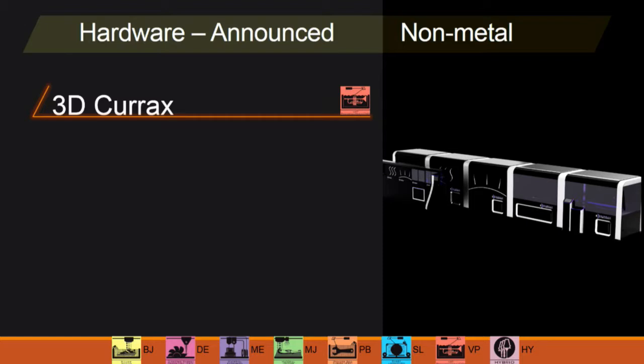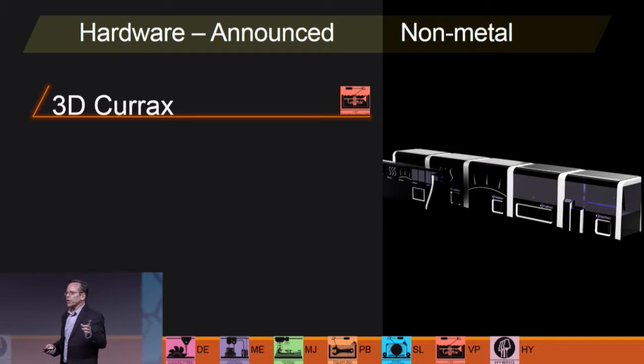Two machines available, the MRK3 and the MRK10. The 3 has an XY working area of a little over 400 square inches. I'm guessing that's going to translate to about 25 inches by 15 inches for XY. The Mark 10 is 10 times bigger, so 4,000 square inches of working space, which is going to get you into probably roughly the 70 to 80 inch range for at least one of the axes.